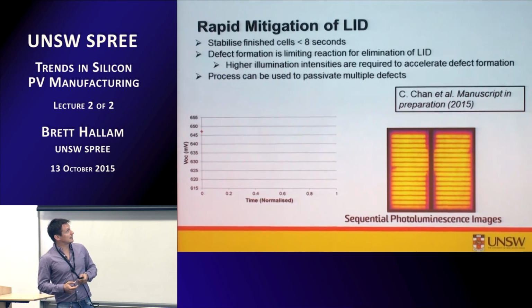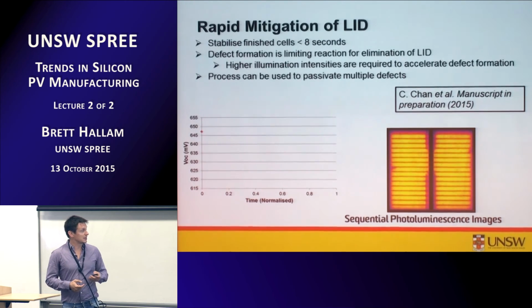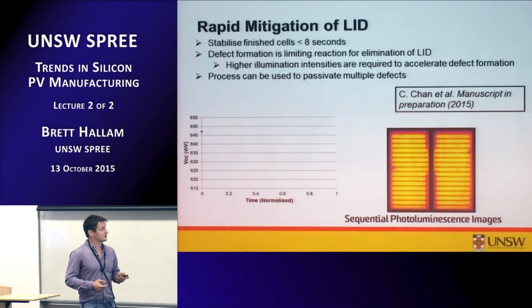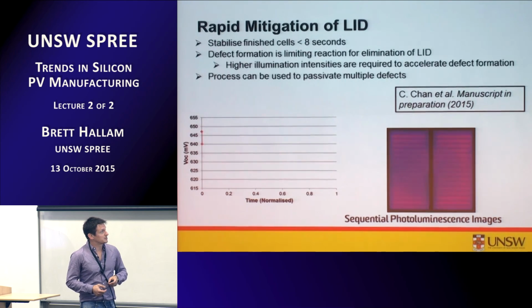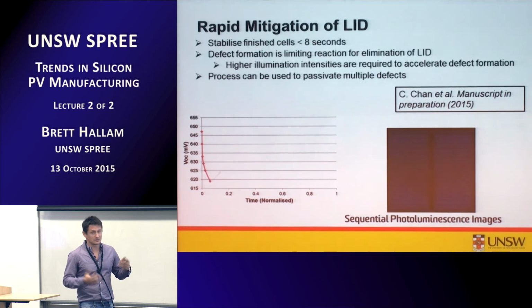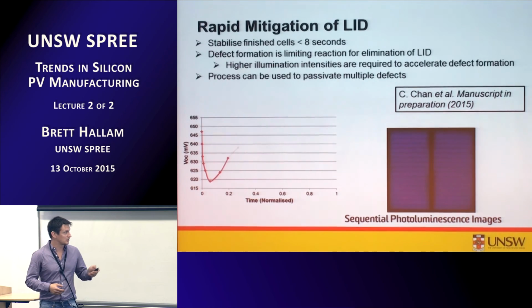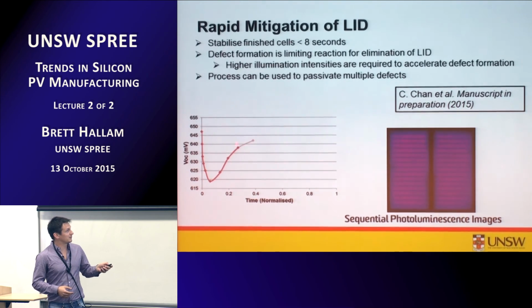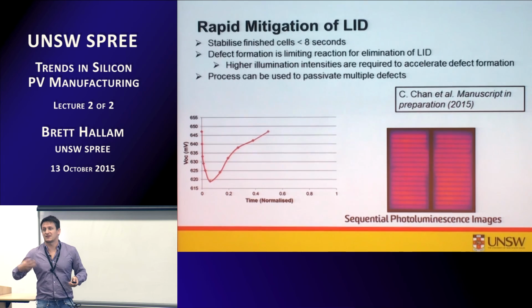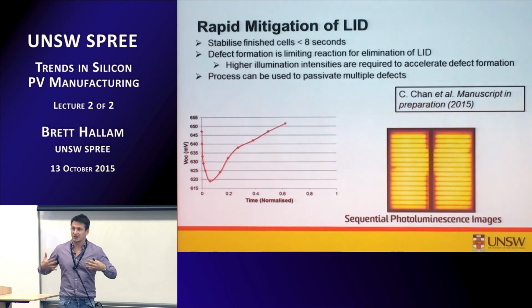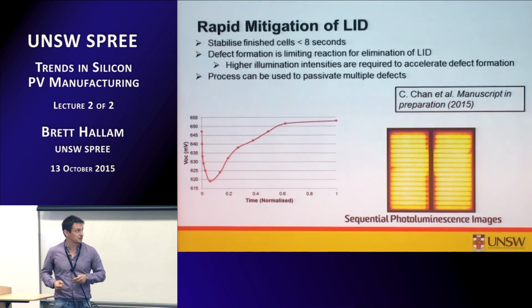So this is a little animation on one of our PERC cells from one of our industrial partners that we've taken off their production line. So we're starting off with a VOC of 645 millivolts, and then we start our laser-based process. The VOC drops down, so the PL response drops down as well. And then you start to see the recovery of the VOC as this passivation reaction starts to dominate, and we get this permanent stabilization of the process.